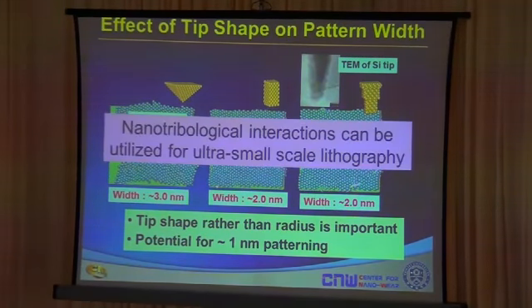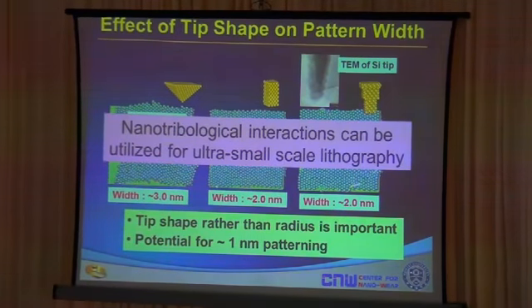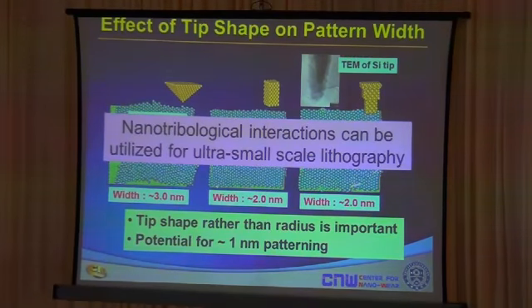So, even for this kind of lithography technique, nanotribological interactions can be utilized, and it's very important because to optimize this process, we have to control the frictional interaction between the tip and the surface, and also come up with the right amount of force to penetrate the film.